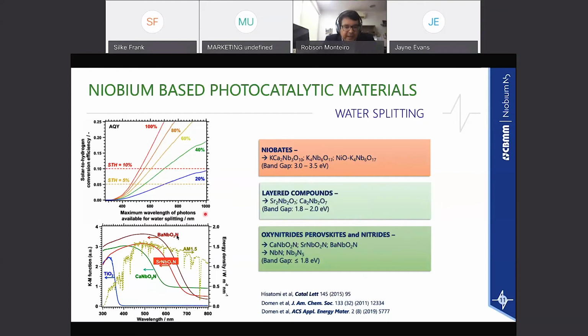Because if you see the plot behind here, most of these niobium oxynitride perovskite type structures have quite good absorption over the visible spectrum of the sunlight. So yeah, if you really want to drive water splitting in the visible light, niobium needs to be part of your photocatalyst composition. That's the message here.